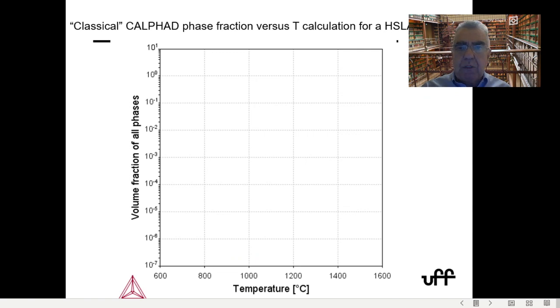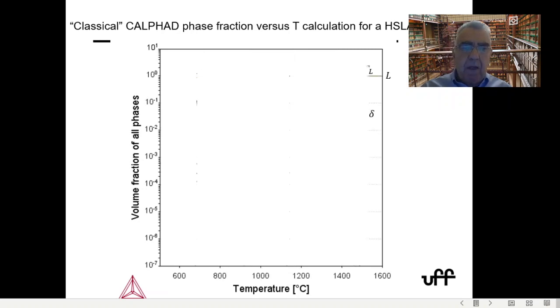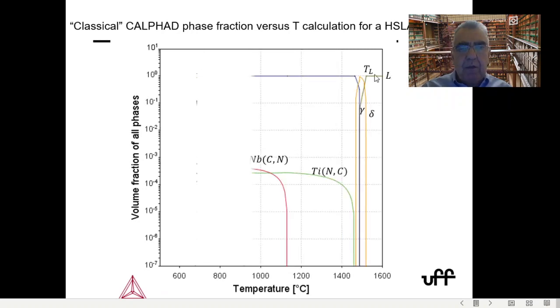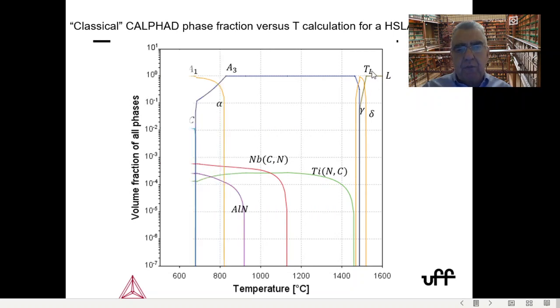So you end up doing this classical temperature versus volume fraction of phases for the steels. If you start with the liquid, you can see the liquidus temperature, you can see the formation of ferrite, you have a peritectic reaction, then you precipitate one carbonitride, which is richer in titanium. I just simplified here, of course. Then a carbonitride that is richer in niobium, more like a carbide, then aluminum nitride, and so on. So this gives you very easily the solubility or the precipitation temperature if you want to reheat this steel to dissolve the carbide and so on in equilibrium.